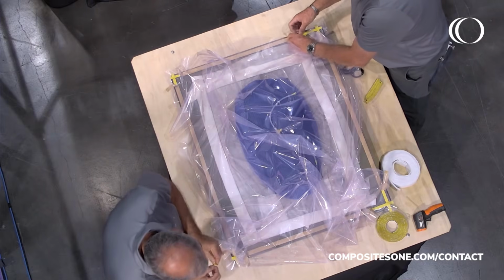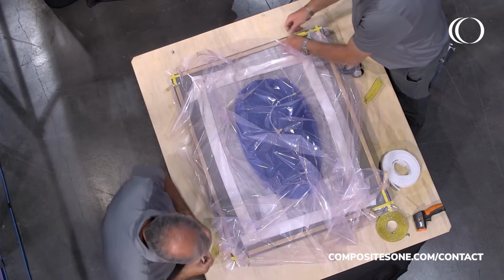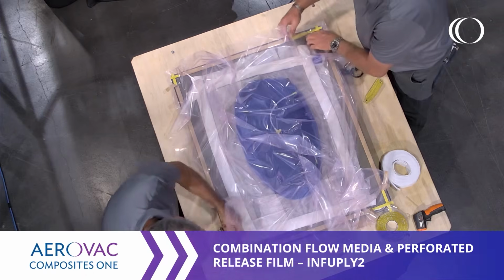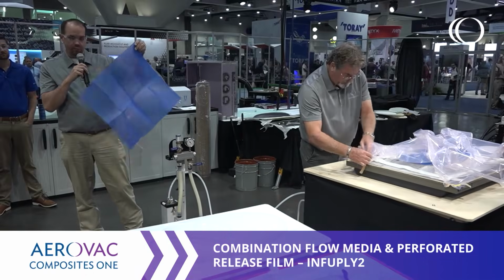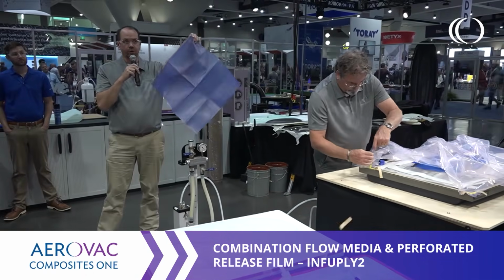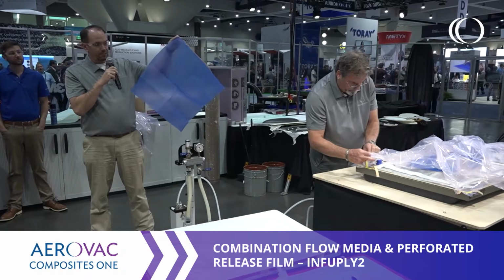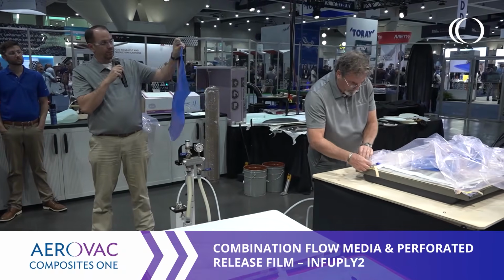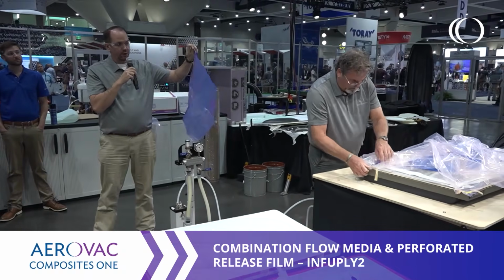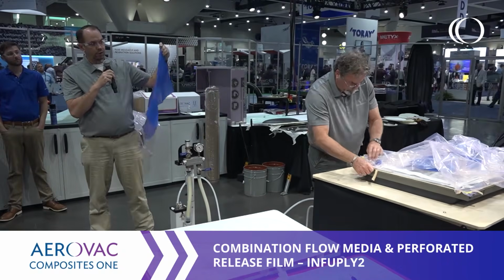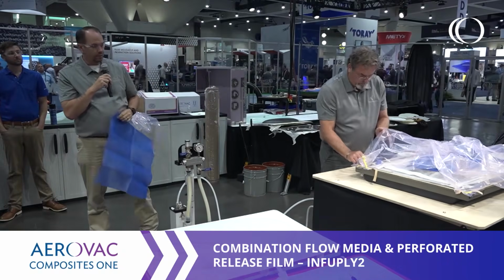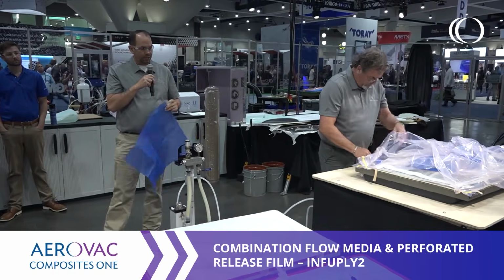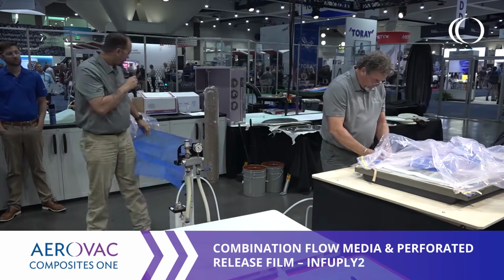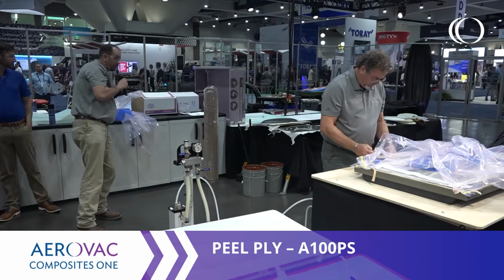Today, you'll notice that whenever they've loaded the preform, in direct contact with the laminate they'll have Infuply 2, which is a combination material for flow media. It has a knitted mesh and then a hot perfed release film on the back side of it, so they can load it very quickly. It is highly conformable, being with the knitted mesh. And then on the periphery of the laminate, they've also got a red stripe peel ply.